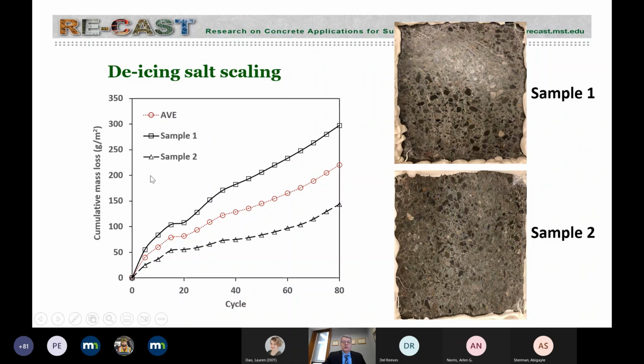We're talking about an average of 200 grams per square meter. Many specifications go up to 1 kilogram after 50 cycles, so 1,000 grams per square meter of scaled out material. So despite the fact that the concrete was not air entrained, the surface is so tight, and there's very little amount of paste, as you know, in RCC technology, that the de-icing salt scaling resistance was very, very high.